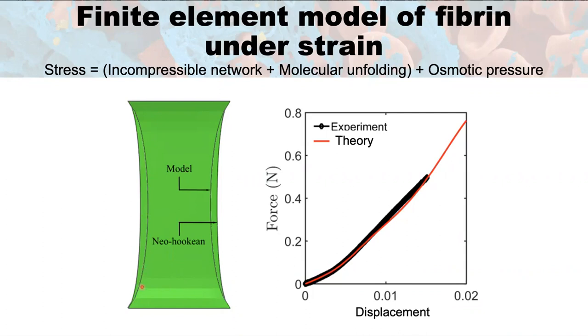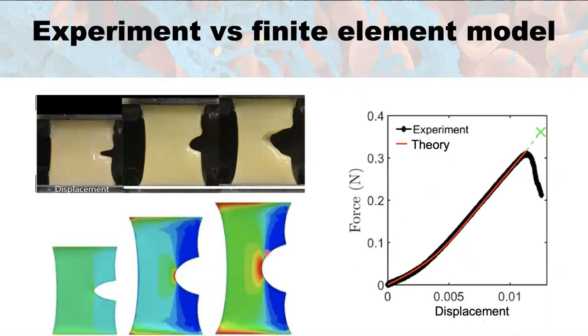And so just like the experimental results, the theoretical approach is able to output these force and displacement curves based on our experimental clots that we're making. And so when we look at the comparison of the experimental with the finite element model, we're able to do a visual comparison, such as can be seen here, where we see increasing displacements resulting in that macroscopic deformation of the gel.